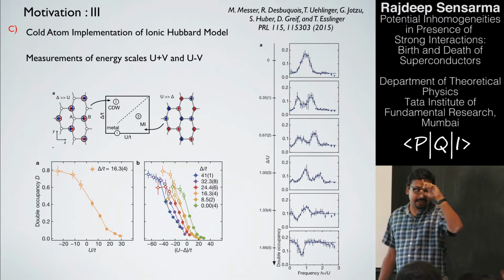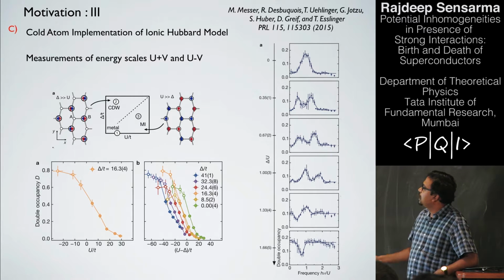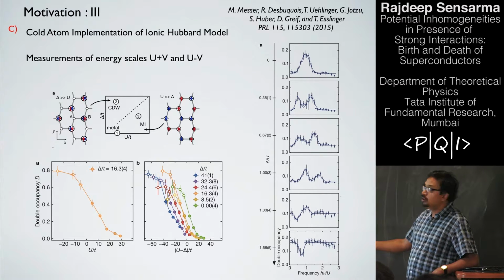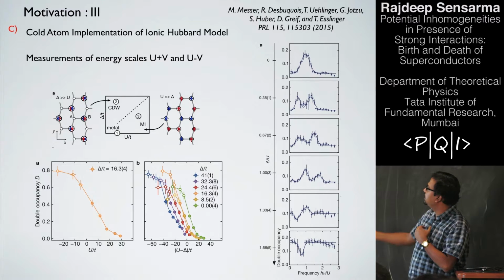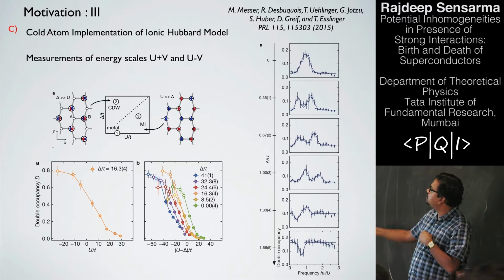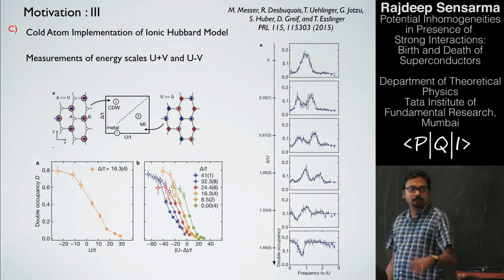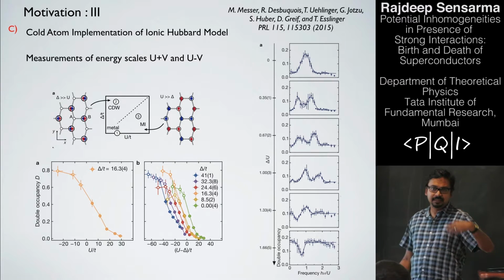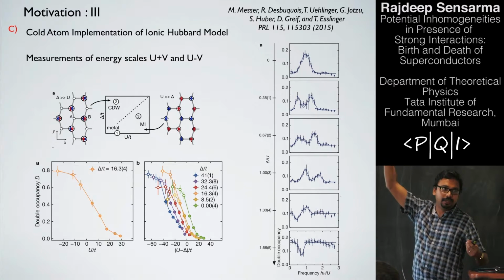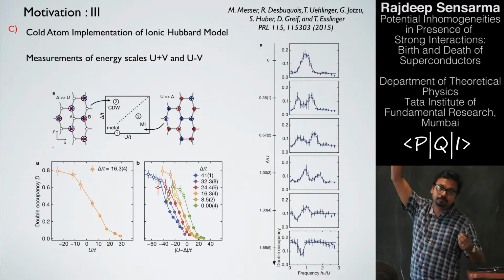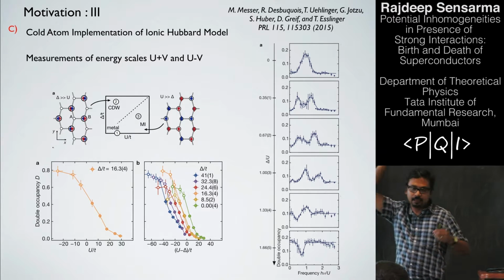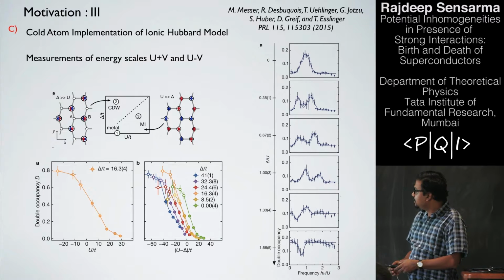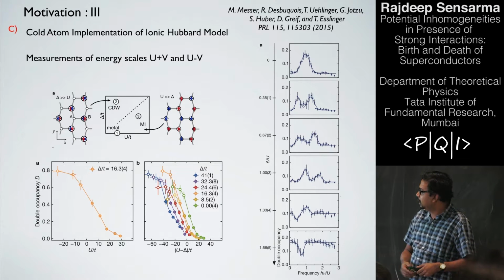Motivation three is in cold atoms. Recently, Tilman Esslinger's group has been able to actually implement this model on a honeycomb lattice. What you are seeing here is that they're doing spectroscopic measurements. And as U becomes close to V, you see that you get two energy scales in your problem: one is U plus V and one is U minus V. These are the energies of the double occupancies when they are sitting on the plus and the minus sublattice, A and B sublattice. And you can see that they can track all of this.